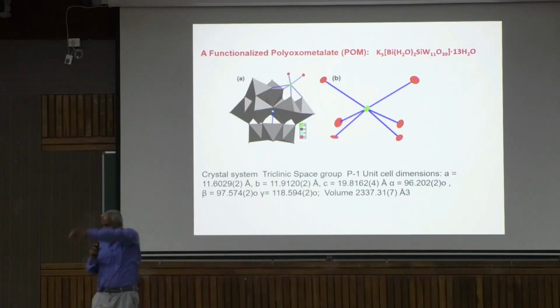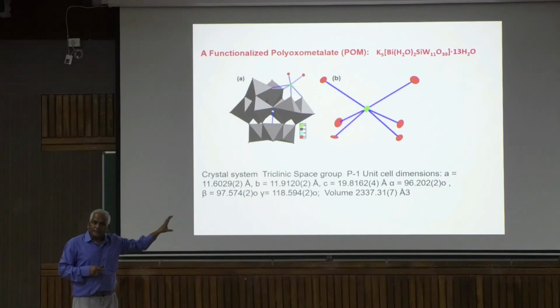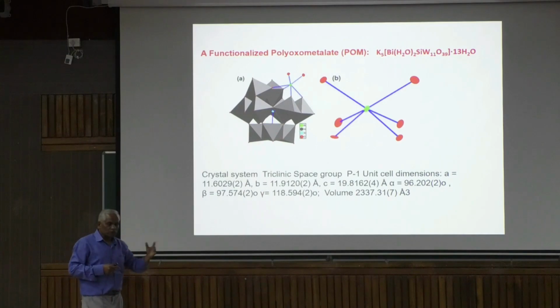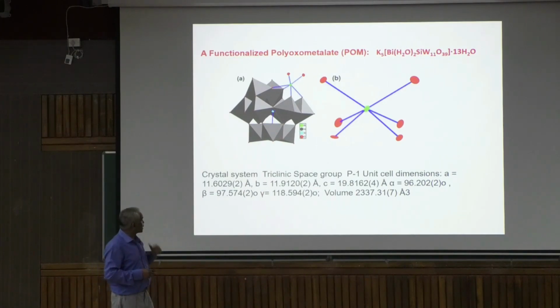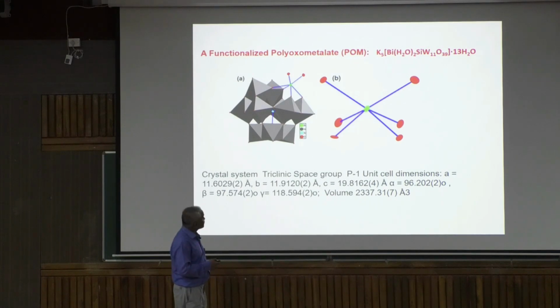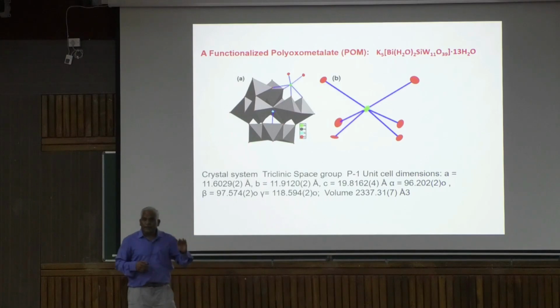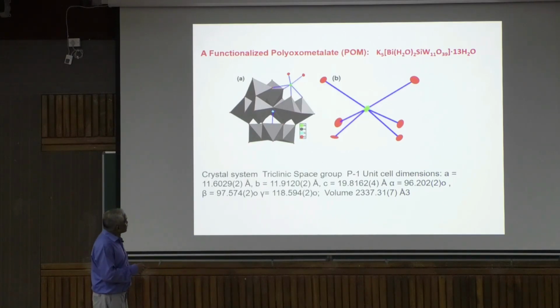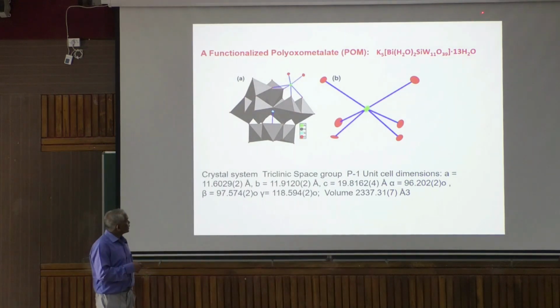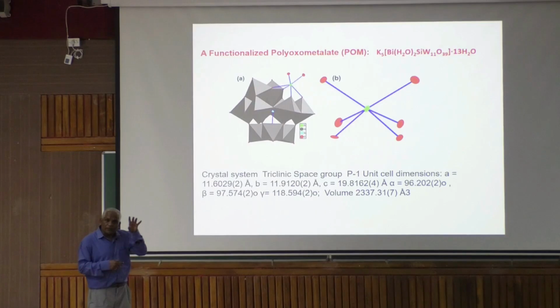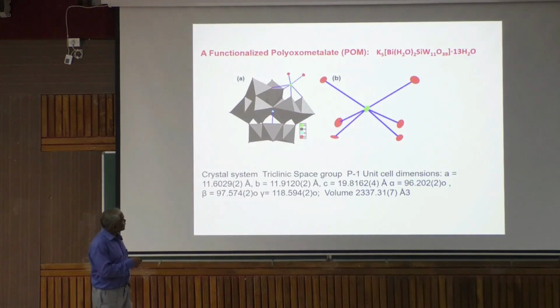Now, because I am talking about polyoxometalate, you saw there that the central cobalt became active because it hydrolyzed and it gives the 4, 3 and 3, 2 couples. Now I am telling you about another interesting polyoxometalate. We could get a single crystal. Let me tell you what this is again: SiW12O40, but you could take out one WO. Then it will be SiW11O39. So we take it out to put in another metal, bismuth and water. What is lacunary again? If you take out one WO from SiW12O40, it will be SiW11O39, and in that lacunary place you add another metal heteroatom, bismuth, and you get this compound.